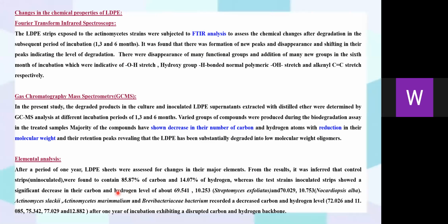Changes in chemical properties: FTIR, GCMS, and elemental analysis. LDPE strips exposed to actinomycete strains were subjected to FTIR analysis to assess the chemical changes after degradation over the subsequent period. It was found that there was formation of new peaks, and disappearance and shifting of peaks. So there was a disappearance of many functional groups and addition of many new groups in the 6th month of incubation, indicative of OH stretch, hydroxyl group, H-bonded normal polymeric OH stretch, and alkenyl C=C stretch respectively.